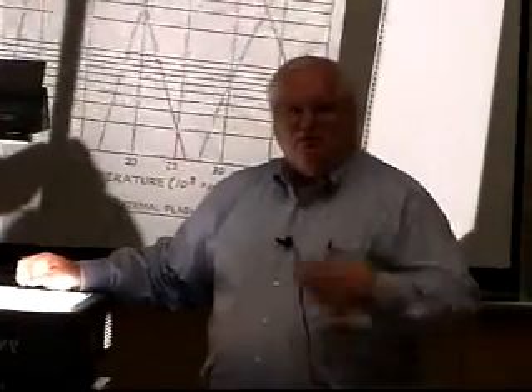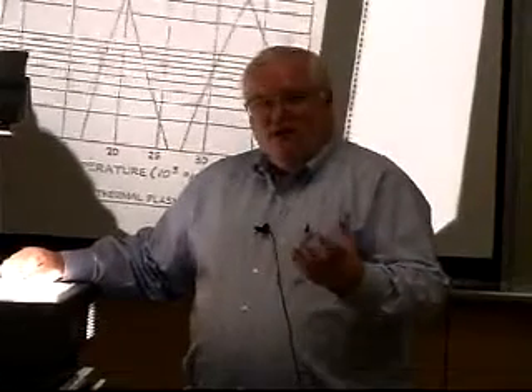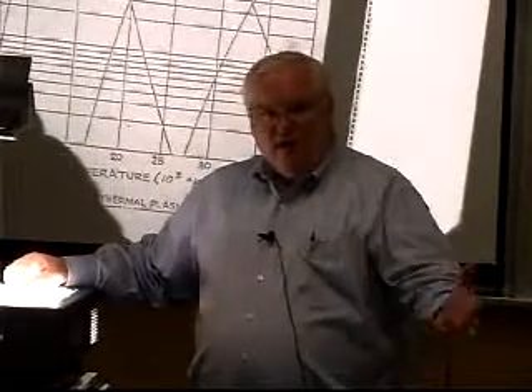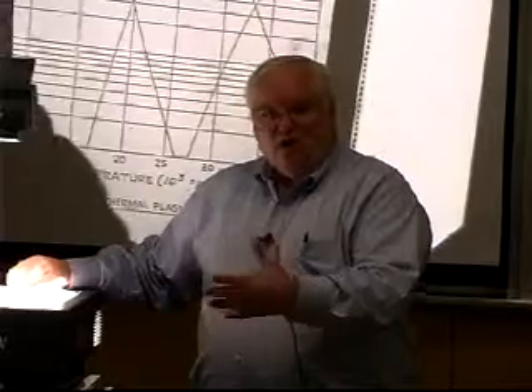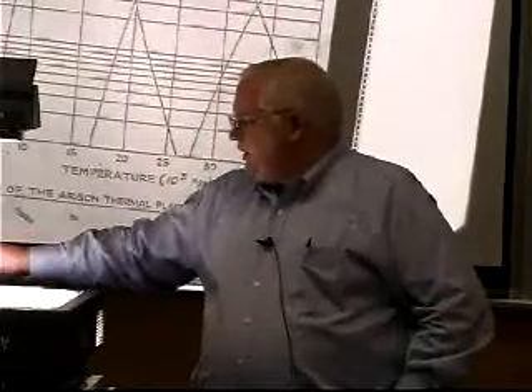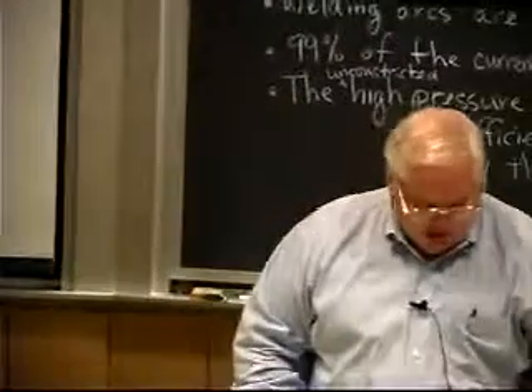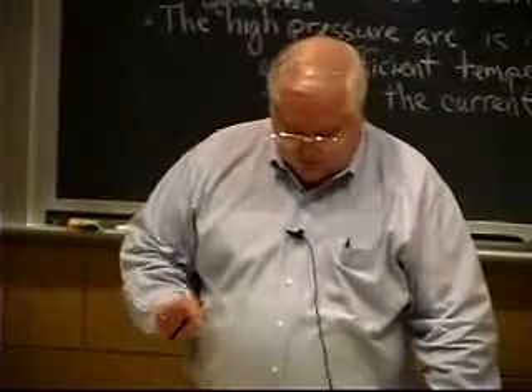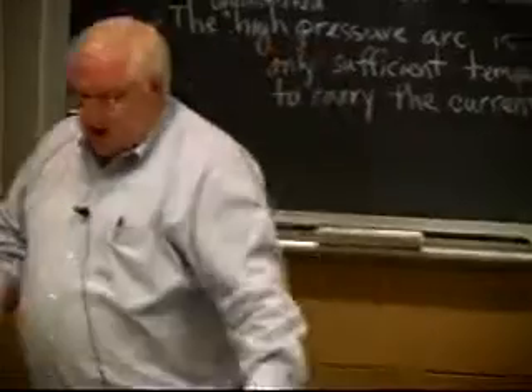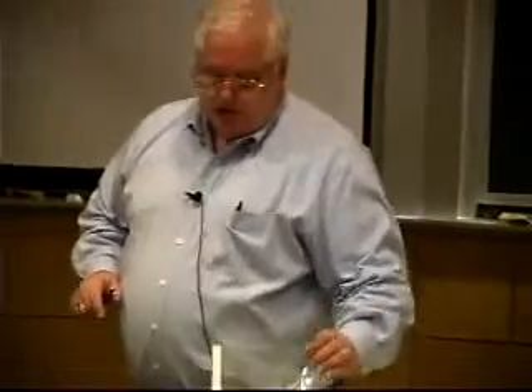And so the actual temperatures of welding arcs as measured are around 10,000 degrees, not 12,000 or 14,000. They're around 10,000 because it's some sort of mixture, an average between a pure metal vapor arc of 5,000 degrees and a pure argon arc, which might be 14 or 15,000 or 12,000 or whatever the number is, depending on the current you're carrying. So there is a different reason why helium does more efficient melting than argon, and we'll get to that in a little bit.